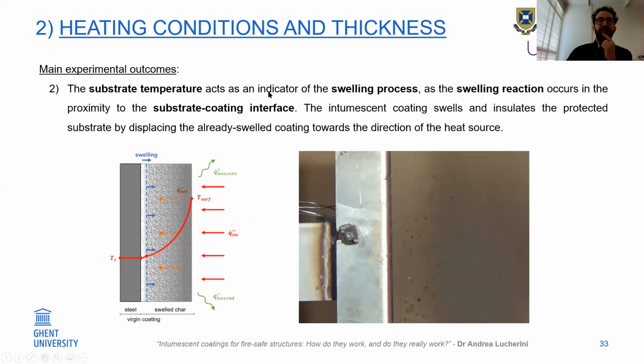In particular, if I remove the laser, you can see that the substrate temperature acts as an indicator of the swelling process, as the swelling reaction occurs in proximity to the substrate-coating interface. So the coating, you can imagine here I have a heat flux that penetrates through the coating close to the surface, it starts swelling, and the gases released by this coating are mainly trapped in the coating. So the intumescent coating swells and insulates the protected substrate by displacing the already swelled coating towards the direction of